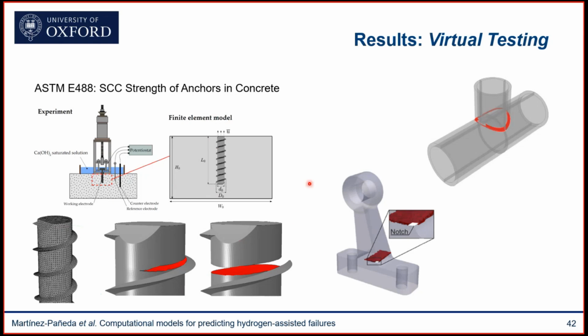You can see that we can simulate the complete failure of the screw, and we can model anything that we want. So we can model large-scale components. We can simulate the failure of large-scale components such as pipelines or any other geometry. So effectively, we're bringing this idea of virtual testing to hydrogen-containing environments, and this was kind of our goal.